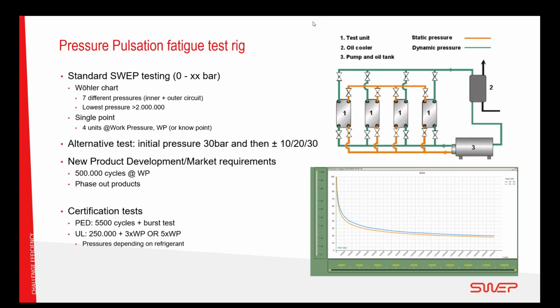Alternative testing can be that you have an initial pressure, and then we pulsate that pressure plus or minus 10, 20, or 30 bars, for example. We also do this testing when we have new product developments or a specific market requirement. We usually see, as a general trend, about 500,000 cycles at the operating or design work pressure. We also do testing when we create new products and phase out the old product, to make sure that we have equivalent or better performance.